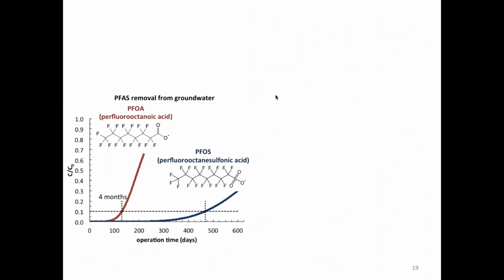To wrap up, I'll show a couple more examples. Here we've done a similar thing considering the Blue Barrel 300 liter per day system and imagining PFAS, perfluorinated compounds, a couple of well-known ones, PFOA and PFOS, in groundwater. This suggests that if your goal is to get 90% or better PFAS removal using the 300 liter per day biochar treatment system, for PFOA you should recommend changing the char at least every 4 months. PFOA is very difficult to adsorb, so it breaks through quickly. We see that also with activated carbon systems.